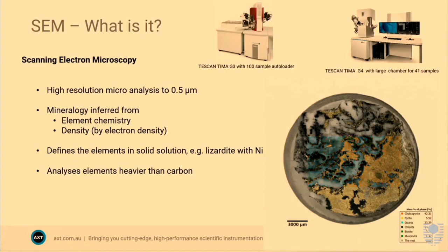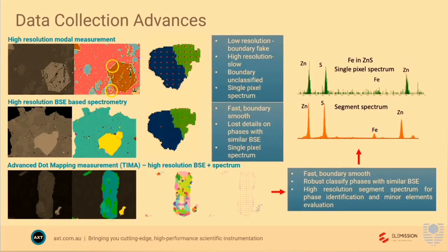This technique came from a void in other analytical techniques. There was nothing around that could scan a sample at high speed, and the applications in the day were for process metallurgy. So instead of point counting down a microscope, it was kind of like automated petrology. There are lots of different ways of acquiring the data. The spacing between points is called resolution. You can collect your backscatter electrons at exactly the same spacing as your X-ray photons. The way the technique works is that you set a threshold where you ignore everything less than a certain value, and then you start recording the spectra of whatever is above that.